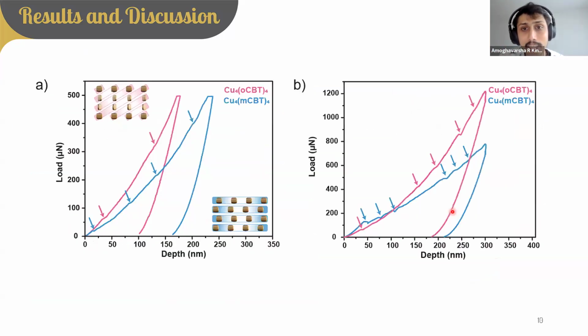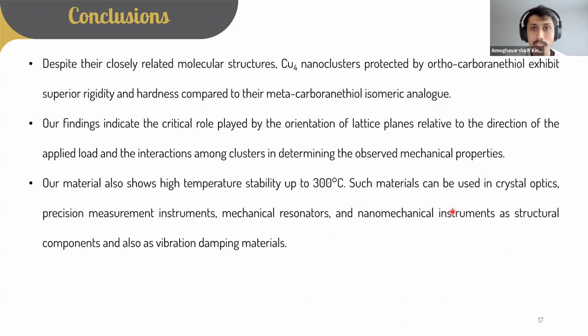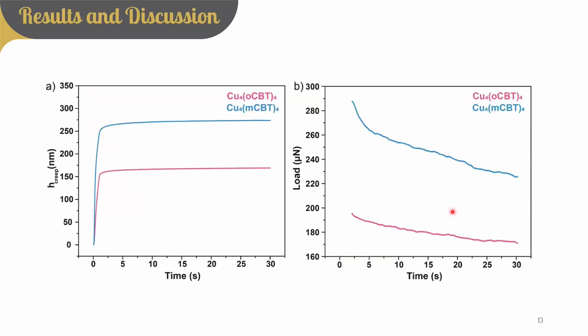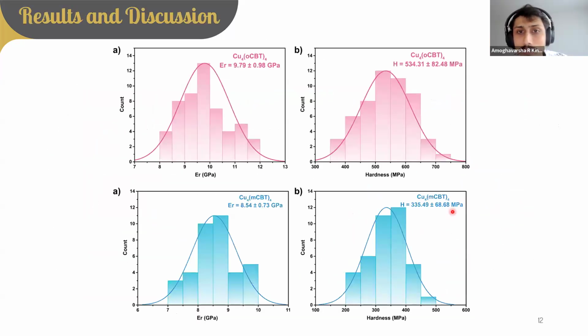Even for single crystal XRD measurements, which I mentioned in the future directions, we have to probe the X-ray onto that point and study the changes in the structure at that point, under the tip of the indenter. Doing the X-rays, from my understanding, is not possible, because the micro focus X-ray will be 150 micrometer size, and the indentation is very small. Correct.